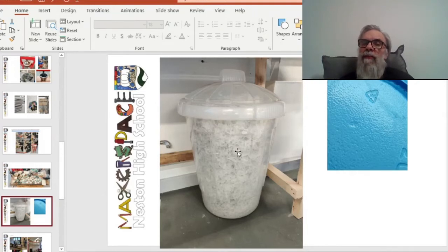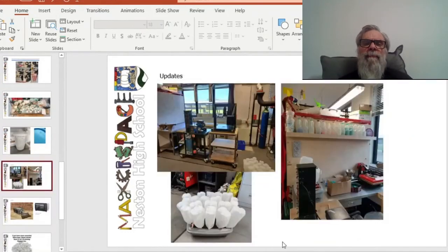So you can see this is an 80 litre drum that is full that we've shredded. Our shredder, we have to shred this 3 times to get a very fine shred, because it gives quite a coarse shred. On Precious Plastic, there was a good write-up about that. It depends on the amount of teeth you have in your shredder. It depends on the amount of sieve you have, and we don't run a sieve underneath it. We just shred it straight through. And if you sieve it back up into the shredder, you can get it reduced down to a certain granule size.